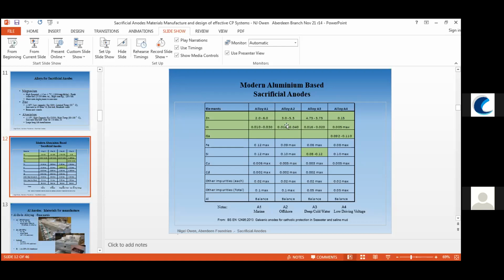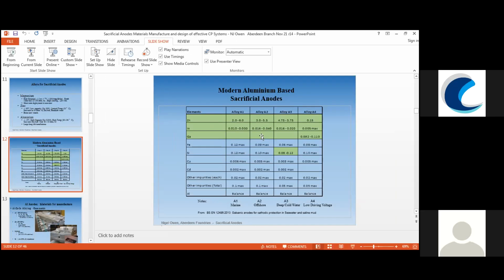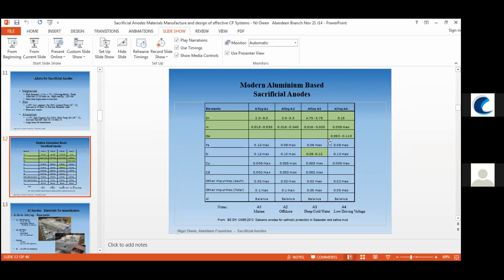Ignoring most of the other elements, we then move up to alloy A2, which is similar to a NORSOK M503 standard material, which is universally used for offshore use to water depths of up to about 300 meters, I believe. And below that, for stability, or people wanting more reliable materials, they're using a refined range of zinc, a higher level of zinc, a higher level of indium. And what I've neglected to say here is that the main refinement in all these is the reduction of the iron, and to some extent, the reduction of the amount of copper, which is an impurity.